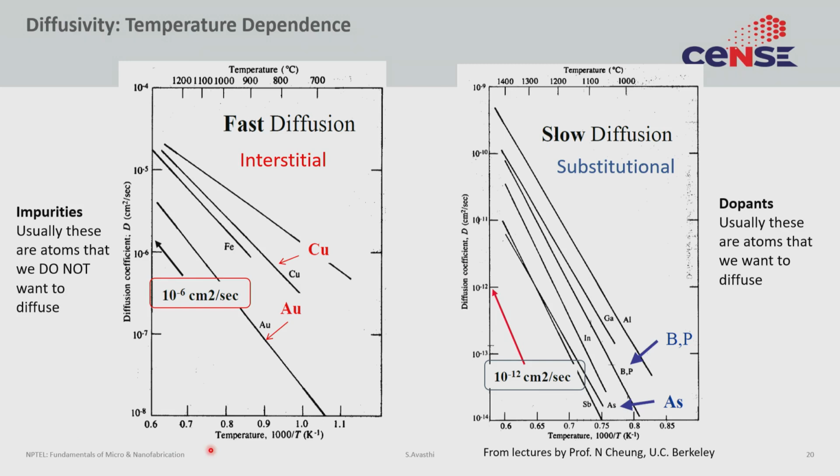is a problem. So, if in your diffusion you have any impurity, any metallic impurity, metal impurity coming because the furnace is unclean, or because you have kept the wafer on top of a metal piece during annealing, all of those metal impurities will go much deeper inside your silicon substrate than your dopant atoms will, and that is why purity is so essential.